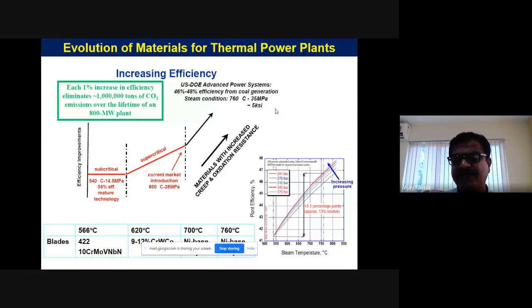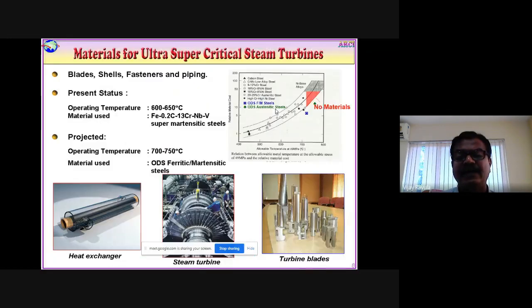So the whole material needs to withstand that kind of stress and that kind of life, around 1 lakh hours, both in terms of creep and fatigue life. Conventionally, iron-chromium steels are used up to 600 degrees centigrade, but beyond 600 degrees centigrade there is no material available. If you go to 700, you are straight away going into nickel-based alloys.